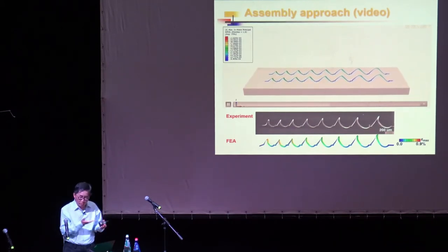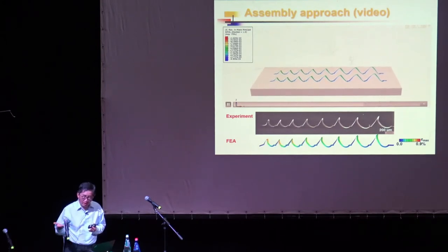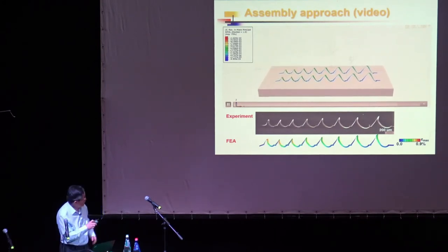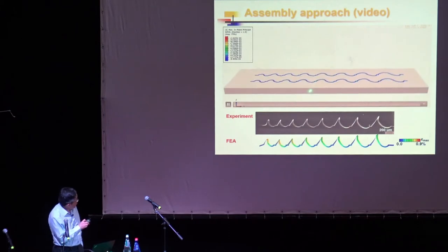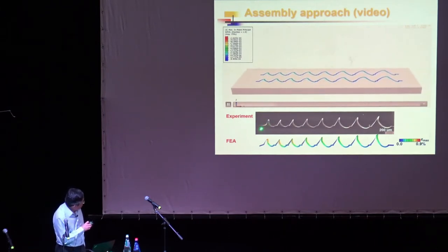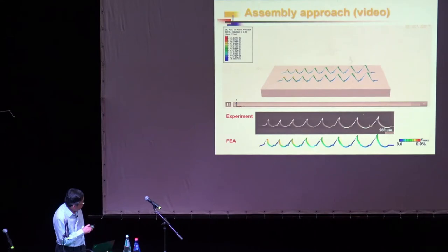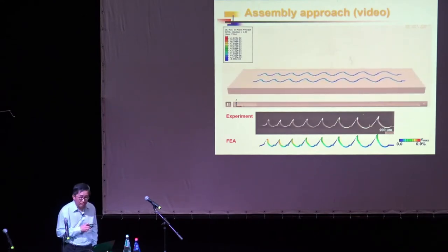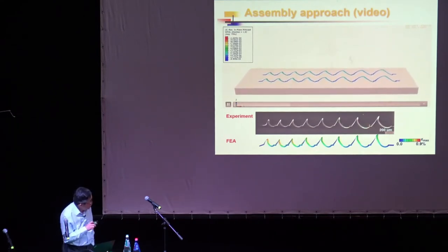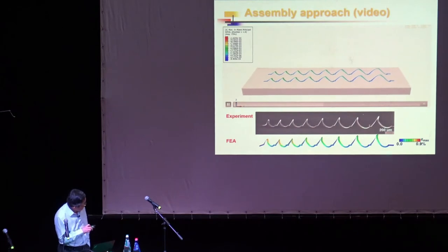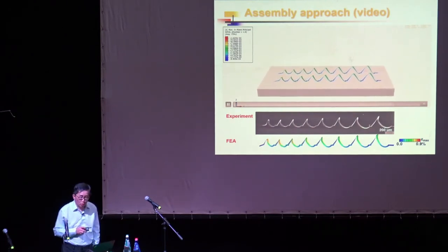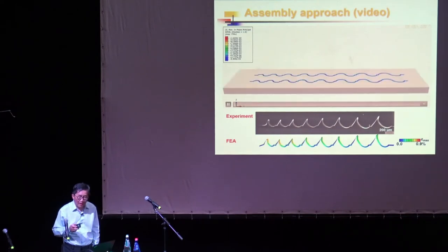Basically, 2D to 3D. And 2D is the semiconductor fab. 3D is the shape we want. And the bottom one here shows the SEM image of three-dimensional wavy silicon. And this is the mechanics prediction of the same pattern. You can see very good agreement in shape. But the mechanics prediction has colors here. We use color to represent the strain level in silicon.